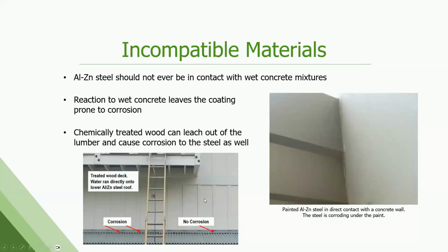Wet concrete, got to have a barrier. Wet concrete against the edges of this coated metal causes corrosion issues. Again, the paint starts bubbling off is your first indication. Chemically treated wood can be a problem. They're usually treated with copper compounds, and copper and pre-painted metal don't get along very well.